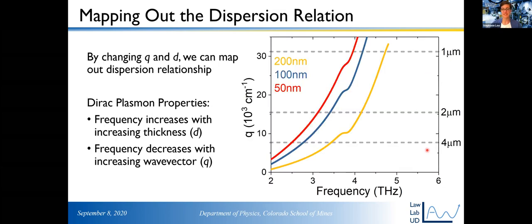So we wanted to see, can we see these Dirac plasmon polaritons, right? People hadn't looked. We wanted to see if we could see them. These are theoretical curves showing for three different film thicknesses what the dispersion curves look like. Again, this is the wave vector of the plasmon, and this is the frequency. So you can see as we change the film thickness, the dispersion curves move. And we're gonna do basically the same thing that we did before, right?